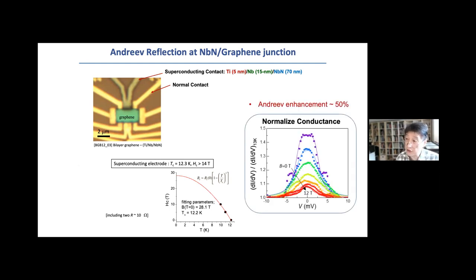Indeed, when we measure the Andreev reflection in this type of device with this combination, we see that at zero magnetic field, about 50% conductance enhancement, indicating that indeed we can make fairly good contact onto this device. And with the magnetic field, of course, with various regions, the vortex formations, this conductance enhancement actually reduces. In other words, the Andreev reflection efficiency reduces, but still up to 12 Tesla, we get about 10% enhancement. So I think it's still reasonably effective, such that we can realize the experiments combining quantum Hall edges with the superconductor.